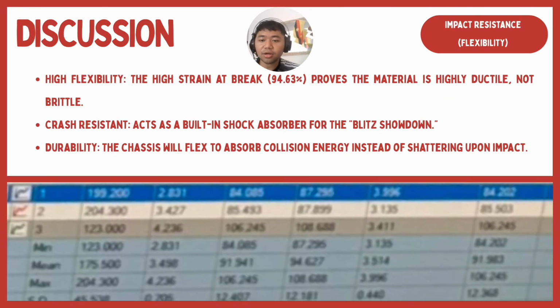Next, let's talk about flexibility and impact resistance. This is where our material choice really benefits the RC gameplay. The testing showed an exceptionally high average strain at break of 94.63%, which proves that this epoxy composition is highly ductile rather than brittle. During the fast-paced Blitz Showdown, our ram and bumper will be constantly colliding with the opponent as well as the ball. Because the material is so ductile, the ram and bumper act as an excellent built-in shock absorber, flexing slightly to absorb and dissipate the collision energy instead of shattering upon impact.